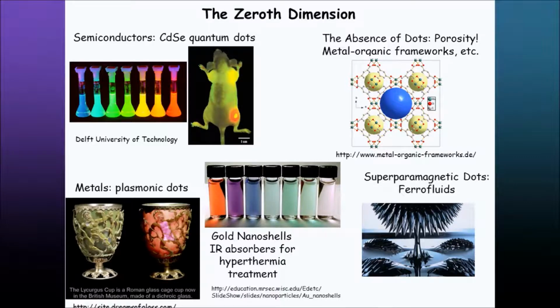And we have the idea then of plasmonic materials, and these are by no means a new technology, and it goes way back to Roman days in terms of gold particles, silver nanoparticles, actually absorbing light in the visible region. And of course, this is in the British Museum. The silver you're seeing there is actually bimetallic silver-gold nanoparticles that give you that silver color in the material. So they even figured out how to make bimetallic nanoparticles way back when.